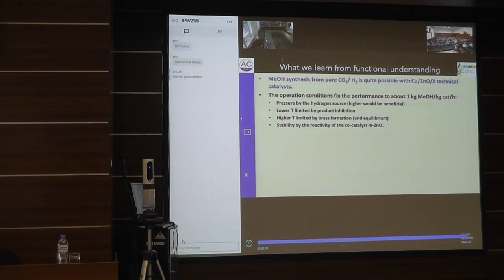The lower temperature limit that I didn't show you is given by product inhibition. We did show that the lower temperature limit is given by the fact that there's a monolayer of methoxy at the surface, and if you go below 200 degrees, this methoxy is simply no longer hydrogenated and it is not desorbing. That means it blocks all the active sites. I did show you that the higher limit is given by the brass formation, but of course you don't want to go to high temperature anyway because the equilibrium is unfavorable for you. So you would like to go to low temperature, but the low temperature is indeed limited by the fact that there is methoxy adsorbing and blocking the active sites.